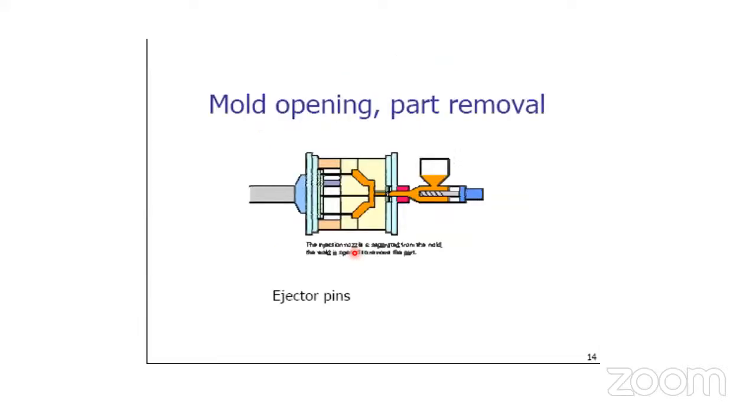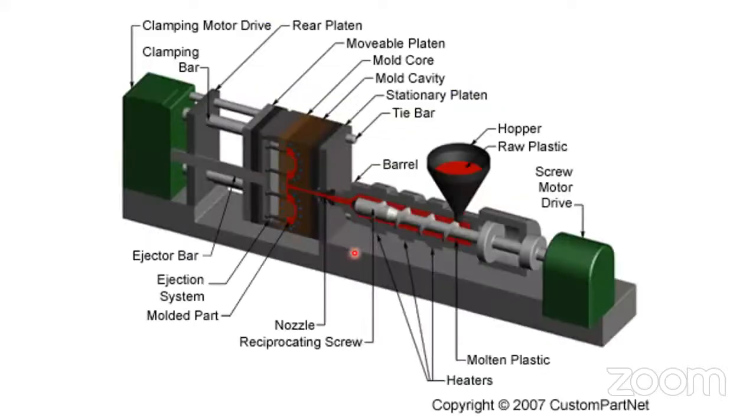Suppose now see here, in this case, this pressure, this is the clamping. The female mold and male mold are closed, and the pressure here is lower than this pressure. What will happen? This is lower and this is the higher pressure. What will happen? The mold is open here, material will come out from this place, and therefore this pressure should be higher. Clamping pressure should be higher than this pressure, injection pressure.